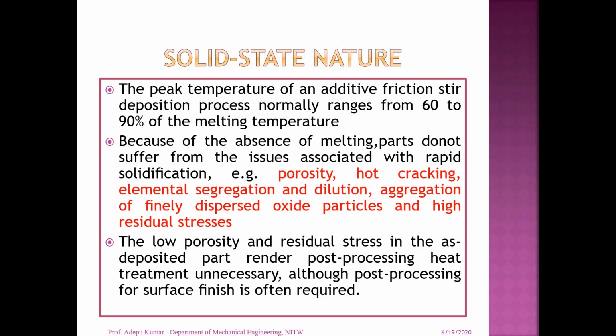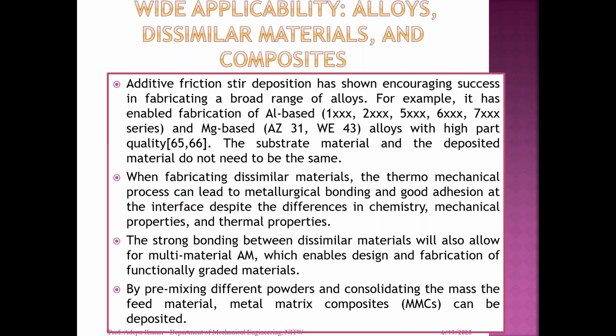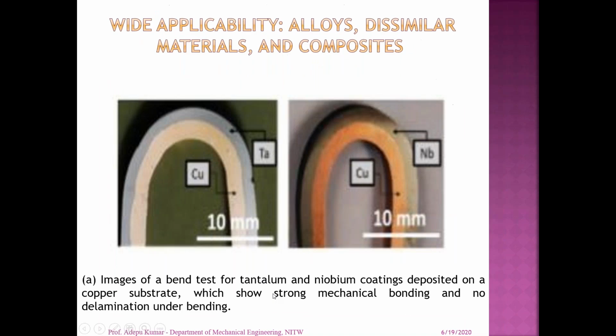He is able to produce additive manufacturing components. So this tantalum and niobium coating is deposited on the copper substrate, showing strong mechanical bonding and no delamination under bending. So niobium and tantalum are deposited onto the copper material. Then you can see there is no delamination of the component. That's why they can conduct a bend test, and there will not be any delamination. There will be a perfect bond between the two, even though they are different materials with different physical and chemical properties. There will not be any difference in the metallurgical aspects.